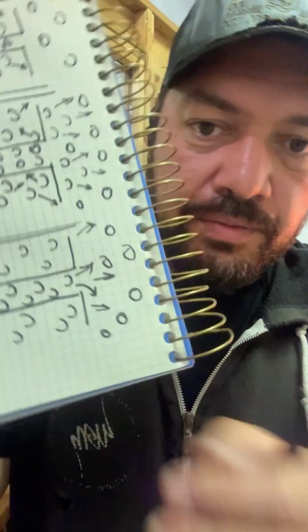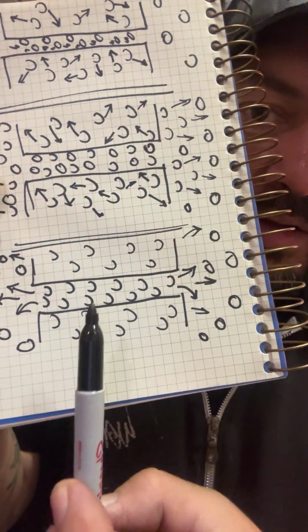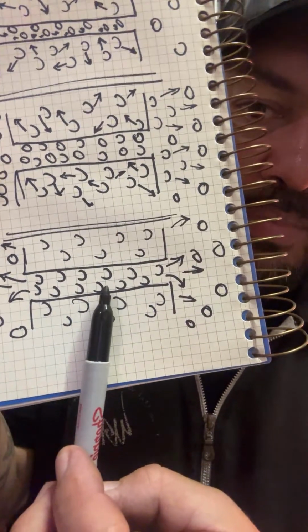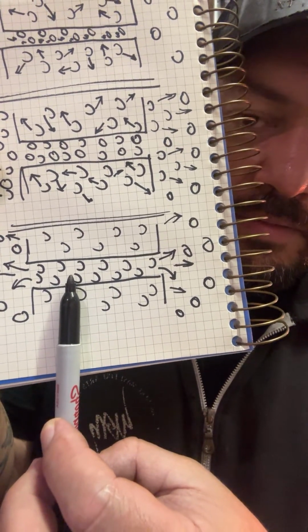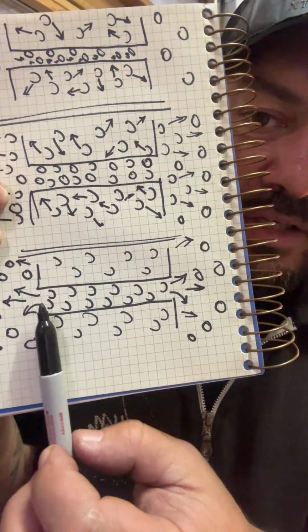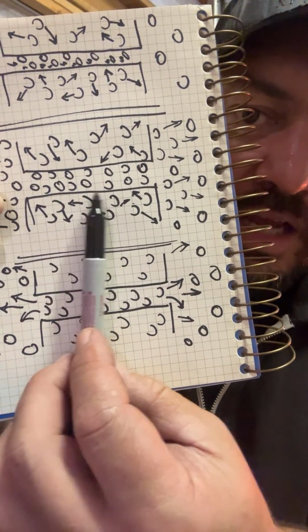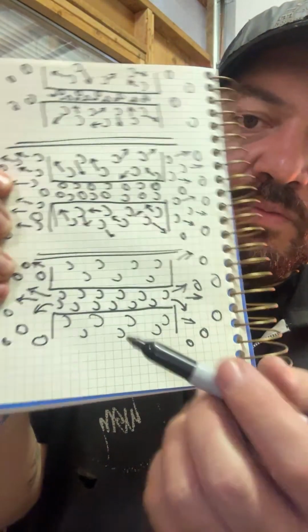Watching me draw, not very interesting. What I'm drawing is very interesting. So it gets to the point where the carbon has pushed out all the oxygen. In fact, not only the free oxygen that's just air, which happens pretty quickly, but also any iron oxide, the oxygen aspect of the iron oxide that has developed on the surface of the steel. Basically, light forge scale. It's not going to be that much, but there's always going to be a little bit.